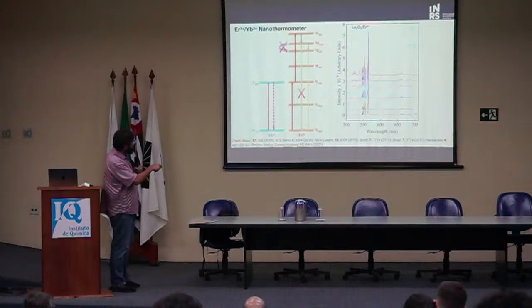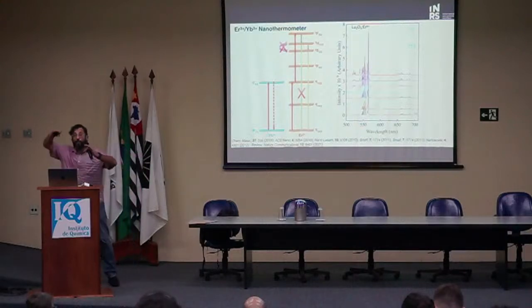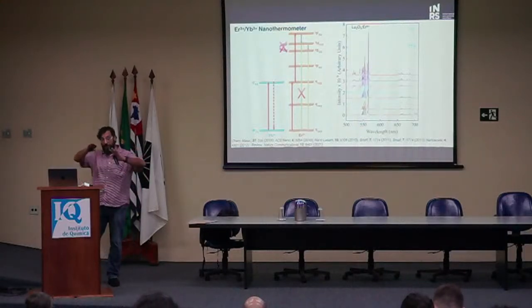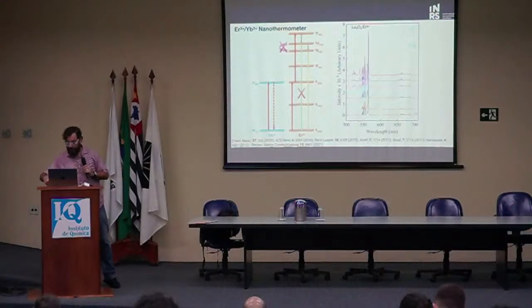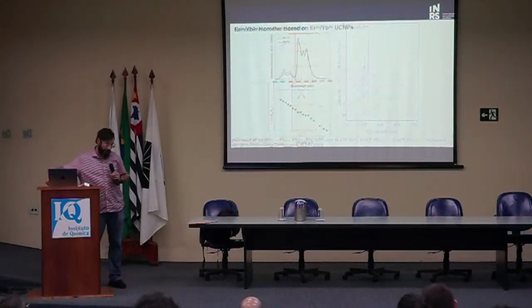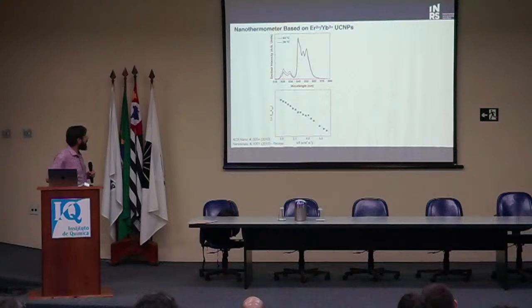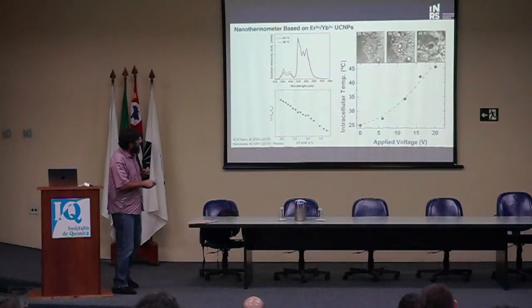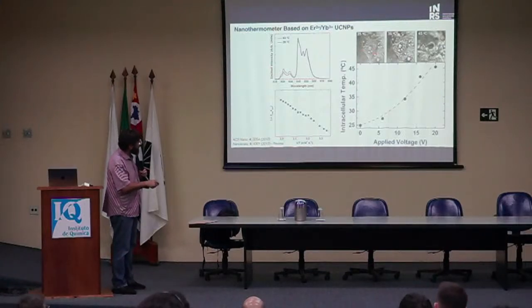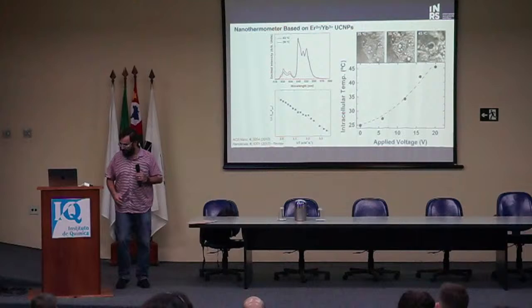Of course, the opposite is true. If you heat, then this becomes much more probable, so you're feeding the state at a greater rate, and this increases at the expense of this guy. So we can correlate that ratio, what we call ratiometric nanothermometry, to temperature. And with Daniel Haki a few years ago, we did just that. We looked at living cells, and we're really the first to show that we can determine temperature in living cancer cells, in the physiological range, based on the ratio of these two peaks, with relative accuracy.